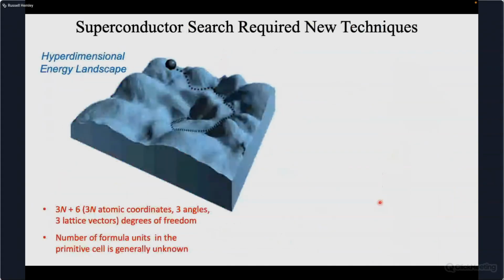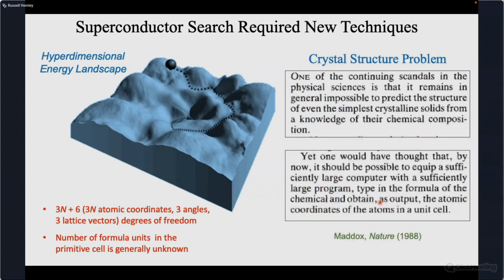So really what made this happen on both the experimental side and the computational side was the development of a structure search method. We had all these ideas about where one might look for these high pressure phases that were in principle predicted or conjectured by Neil Ashcroft, but we didn't know which compositions or what pressure ranges to look for. And so these techniques, genetic algorithm techniques, were developed around 2000. A variety of different approaches were used, and this really also addressed the broader question of the crystal structure problem that was articulated by John Maddox in a Nature paper, where he found it rather embarrassing that we simply cannot predict the crystal structures of materials at high pressure. In fact, this was proven wrong, and within a few years we have a very good approach for doing this, at least for many classes of materials.